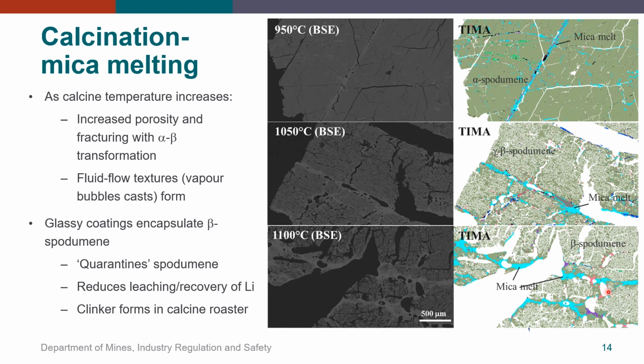The mica melt forms amorphous glassy coatings along internal surfaces that effectively encapsulate and quarantine spodumene from acid leaching. This reduces the amenability of beta spodumene to acid leaching and inhibits the recovery of lithium.